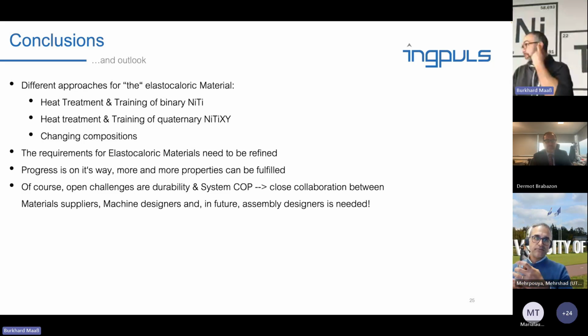and then it's just a brittle material. But we have learned that once you go past a certain point in refining the microstructure, then the material becomes ductile at one point. I see this in NiTi high temperature alloys. I see this in NiTi copper with 15 to 20 atom % copper. When you do the first pass of deformation wrong, it crumbles like a cookie. But if you do it well, then at some point it becomes really ductile, and you can put in a lot of cold work.